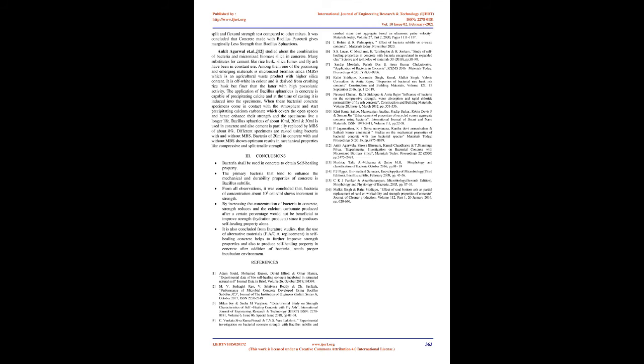Bacillus sphaericus of about 10 ml, 20 ml, and 30 ml is used in concrete, and also cement is partially replaced by MBS of about 8%. Different specimens are cast using bacteria with and without MBS. Bacteria of 20 ml in concrete with and without MBS showed optimum results in mechanical properties like compressive and split tensile strength. Conclusions. Bacteria shall be used in concrete to obtain self-healing property.